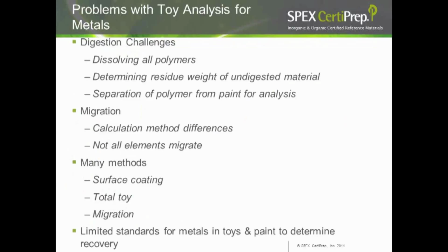For the migration, you have different cited ways of calculating the analytical results. And we found that not all elements will actually migrate at the same rate when compared to digestion. And then there's how do you test your toy? Do you do surface coating testings? Do you look at the total toy amounts? Or do you do a migration study? There's also the problem that there's not a lot of matrix match standards for paint and different toy polymers in order for you to really understand what your recovery is for either an extraction or digestion.